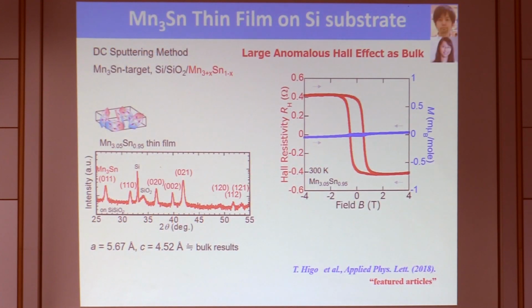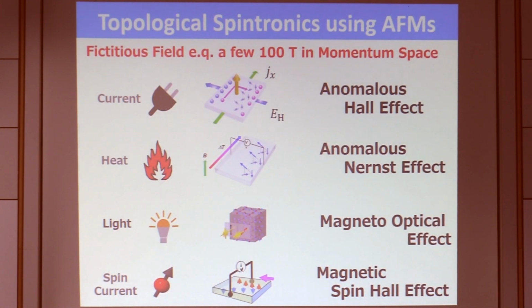We have also succeeded in growing polycrystalline samples or textured samples, and thin films. And this thin film character allows us to enhance the signal of the Hall resistance. If, for example, we use something like 100 nanometers, the Hall resistance change can amount to the order of 1 ohm. So this is a few orders of magnitude larger than what is usually used to monitor antiferromagnetic states in thin films. Although I don't have the data, we have also seen the Nernst effect, and it produces a similar effect, as we're going to show in the next section.